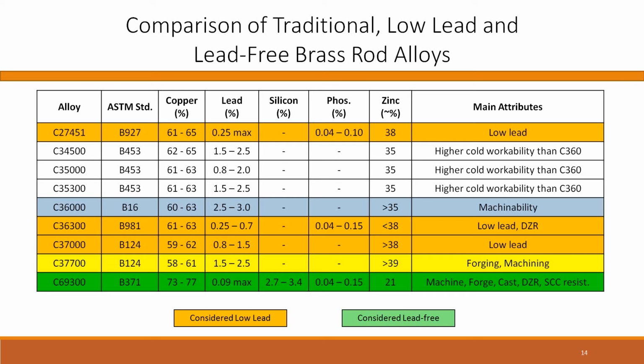The alloys that have come up for the best lead-free, machinability, corrosion-resistant combinations are the ones that are in either darker yellow, should have been orange, more like orange, or green, the green row. And the darker yellow rows are 27451, you can see 363 and 370, that have different combinations of copper. Some designs of potable water fittings can handle more lead than others, so that's why 363 and 370 are in there. The 27451 and the 363 both have phosphorus, which is in there for corrosion resistance. And then the remainder is zinc.